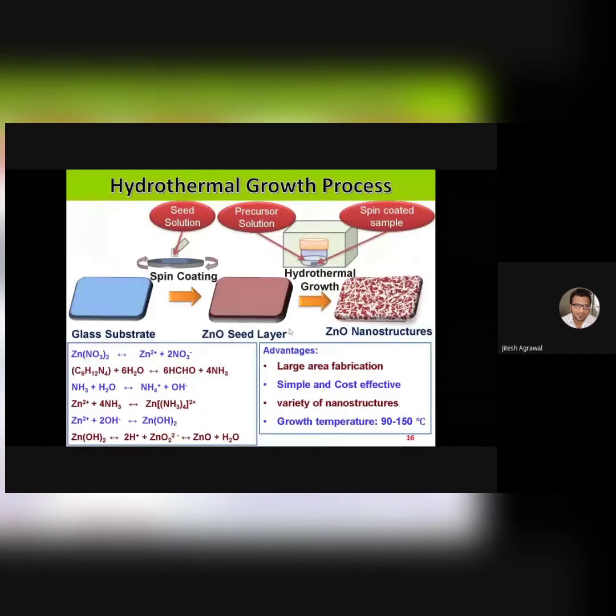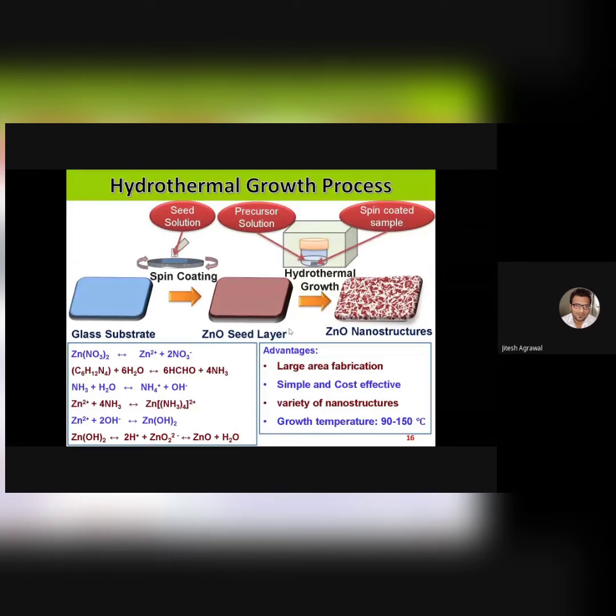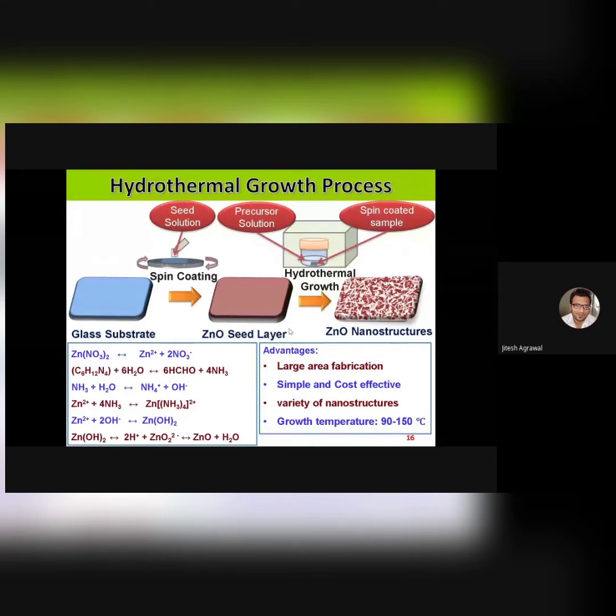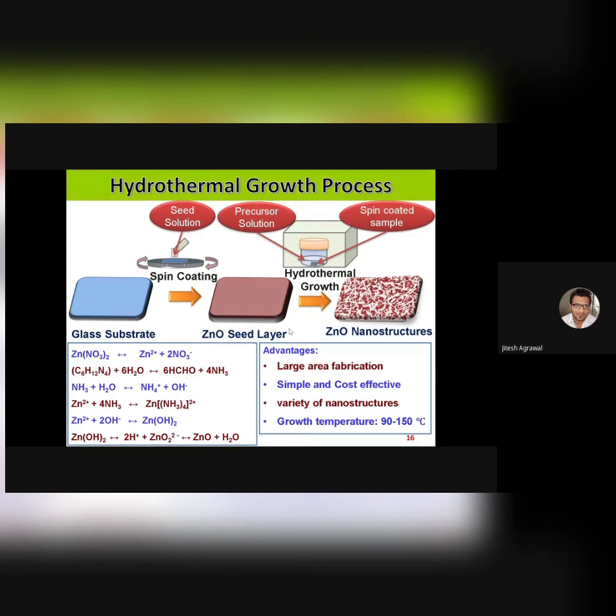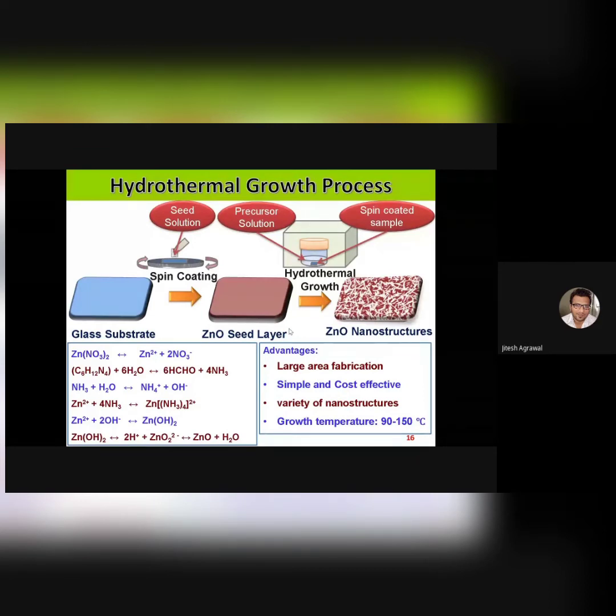Another way to obtain nanostructures is the hydrothermal growth process. In this method, you dip your substrate in the precursor solution and heat at around 90 to 150 degrees Celsius, and you get nanostructures deposited over your substrate. The deposition temperature is very low, so you can work with biodegradable or any kind of substrate not suitable for high-temperature operations. The process starts with chemical cleaning of the glass substrate — ultrasonication in acetone, then IPA, then DI water. In ultrasonication, high-frequency ultrasonic vibrations in the solution remove all impurities from the glass substrate surface.